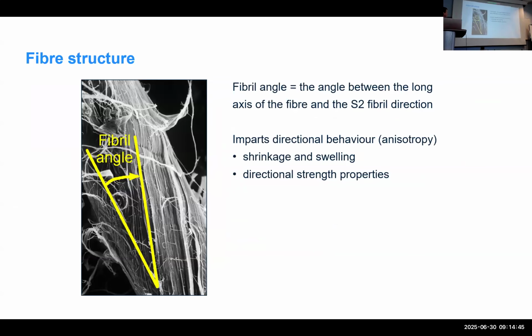And this is a scanning electron micrograph of one pulp fiber where the outer wall layers have been stripped away, and we can see this fibril angle and measure it. And there's all kinds of methods for characterizing fibril angle, and they can be quite involved, but it is an important material property because it gives directional properties to the fiber, the shrinkage, the swelling, as well as the strength properties. These cells are much stronger in tensile along the long axis than they are perpendicular to the long axis. And swelling and shrinkage will go like that. Anisotropy is what I call it. I think other people like the term orthotropy.